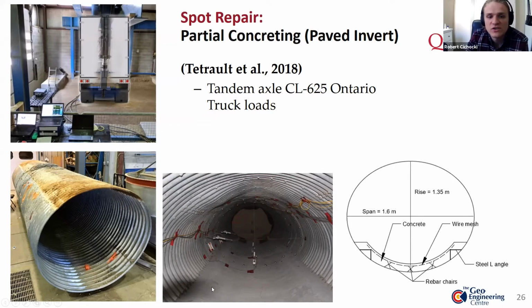This rehabilitation technique generally involved having L angles welded to the bottom of the haunches of the structure, as well as wire mesh sitting on rebar chairs. After the reinforcement was put into place, the invert was cast with a Portland cement concrete that had a 7-day compressive strength of 30 MPa.